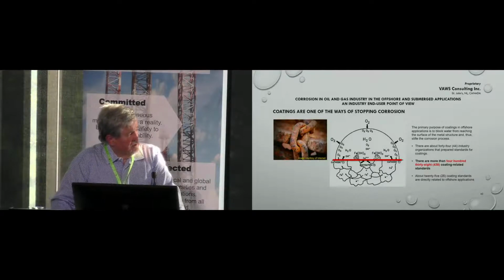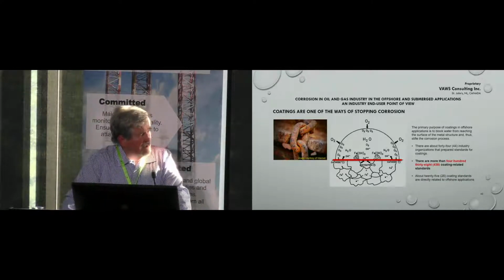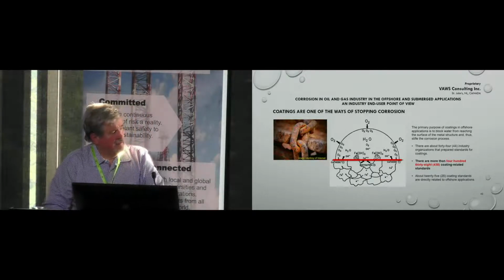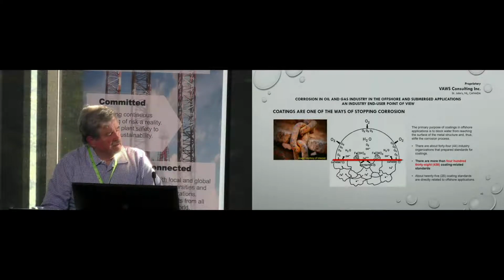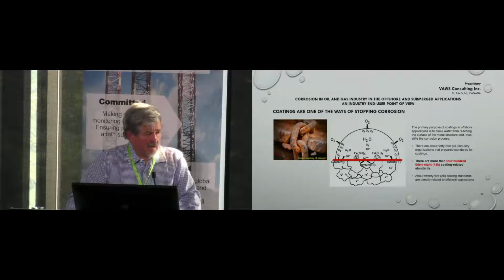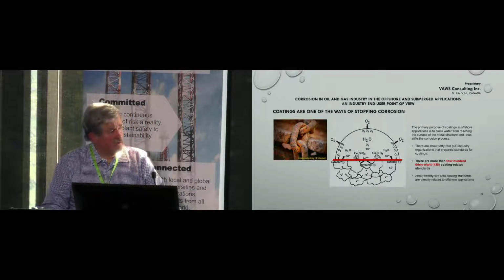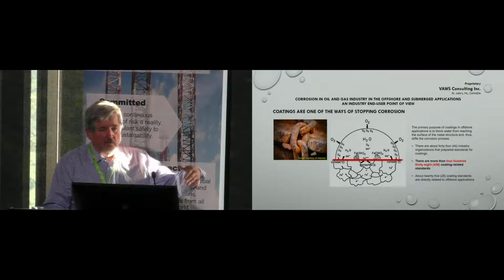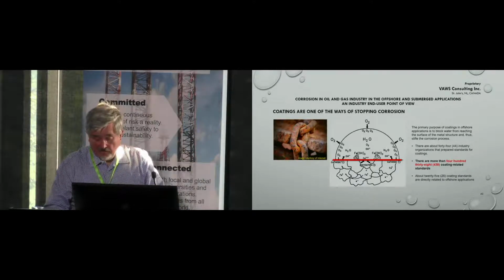How do you stop corrosion? By paints. It's very simple, because what you do is put a barrier between the metal and the water. Don't think that coatings are very dense and they do work immediately. Coatings are like Swiss cheese. They are full of holes if you take them under a microscope. They degrade with time. They are affected by UV. And eventually, you will have permeation of water below the coatings, and that's when the trouble starts.